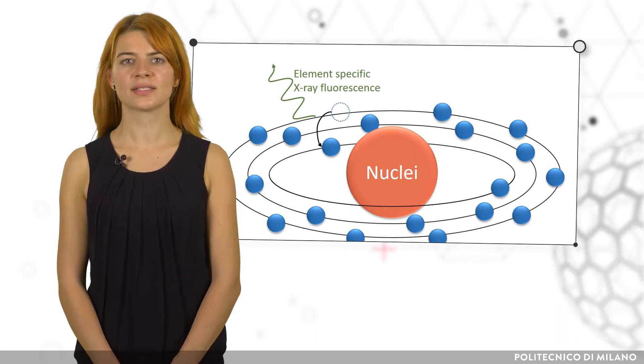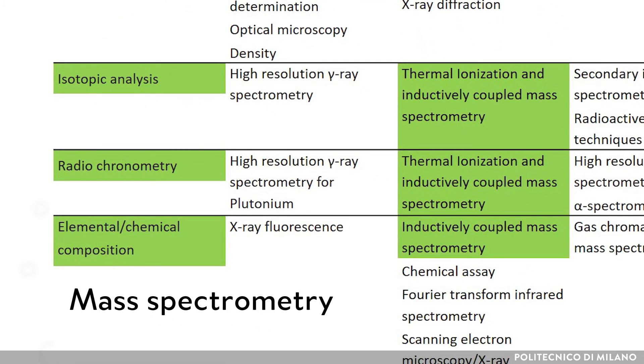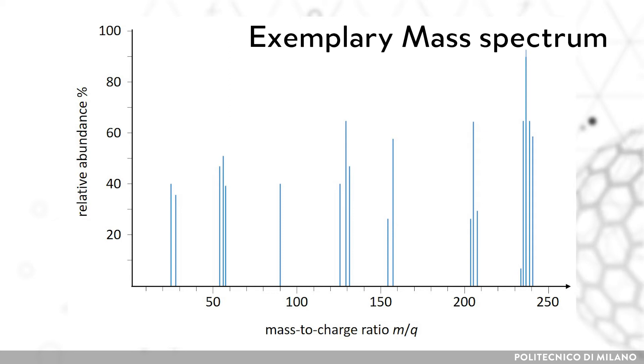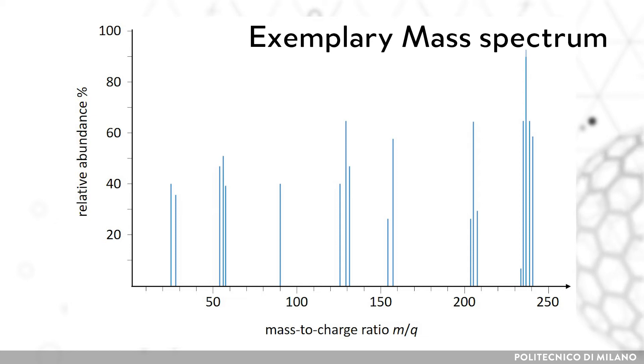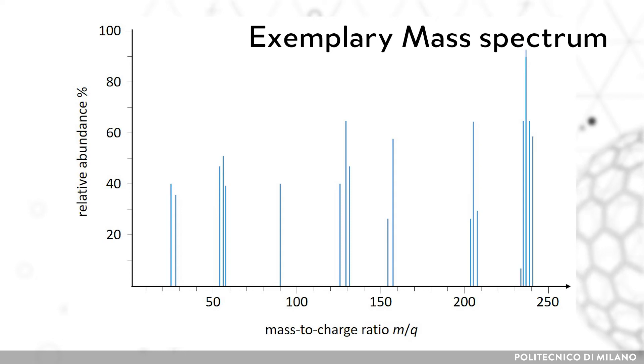In the following weeks, the primary results will be verified and specified. Mass spectrometry is an important tool for this purpose, as it can be used to determine not only the elemental but also the isotopic composition by considering both radioactive and stable isotopes. In mass spectrometry, ions are separated according to their mass-to-charge ratio, and the separation can be done in different ways. The subsequent detection is usually performed by electron multipliers, microchannel plates, or Faraday cups. Depending on the mass spectrometer used, the information obtained and the sample preparation will vary.